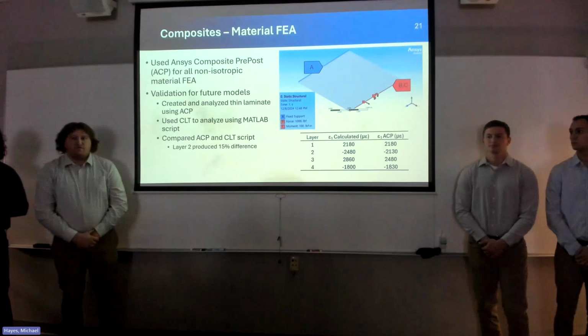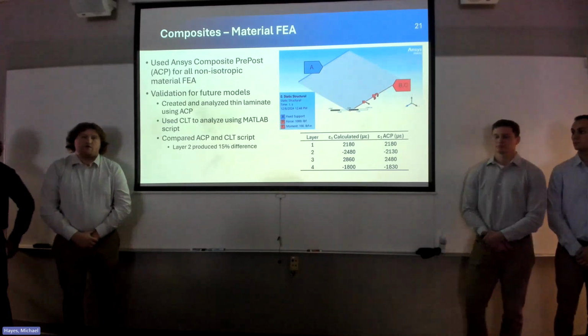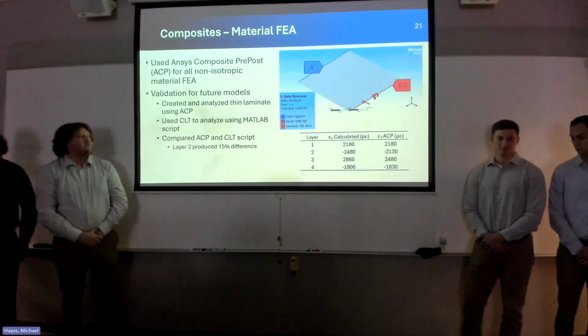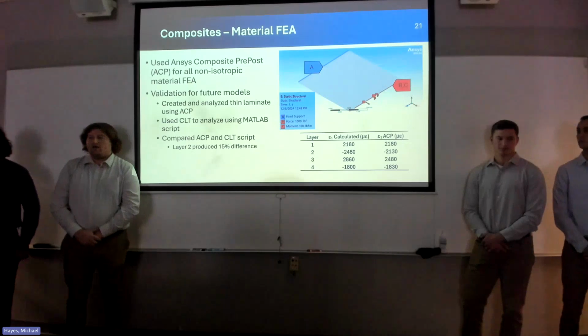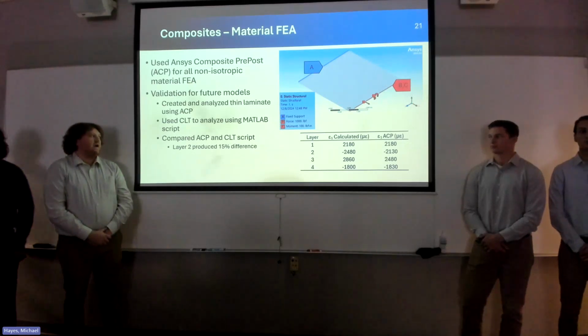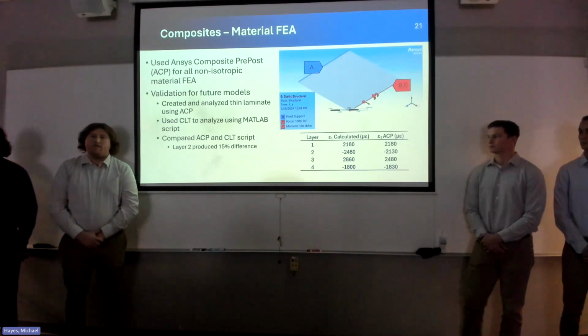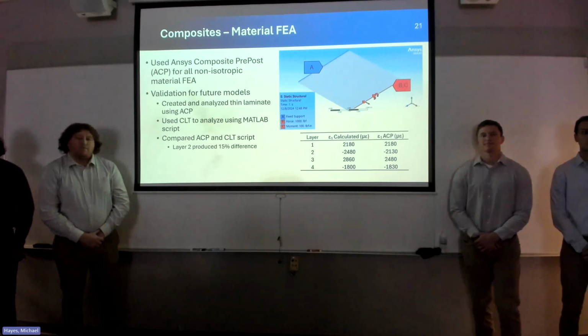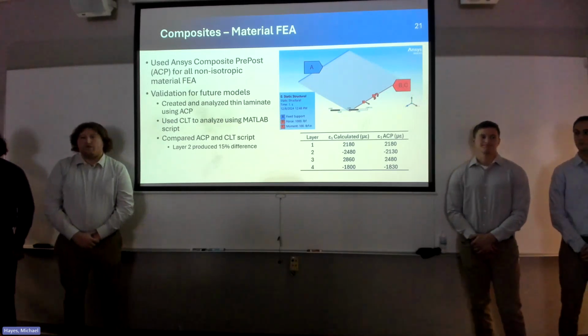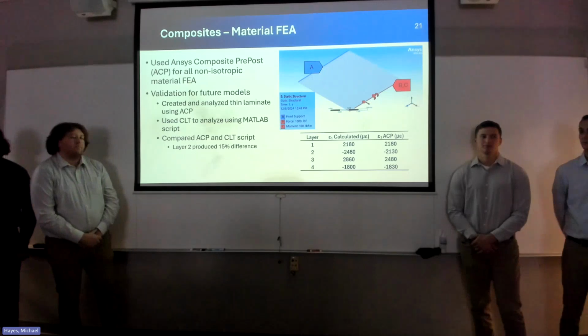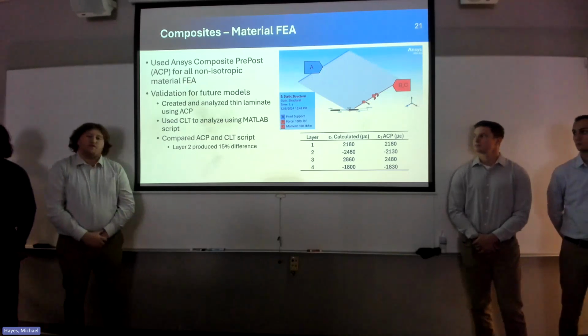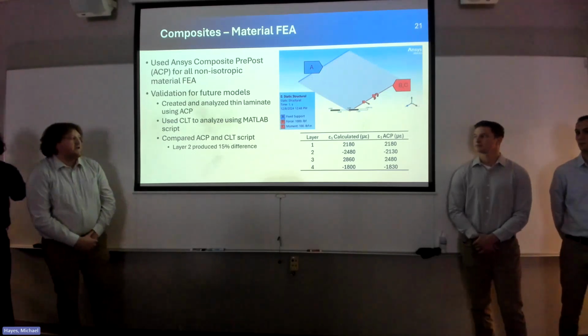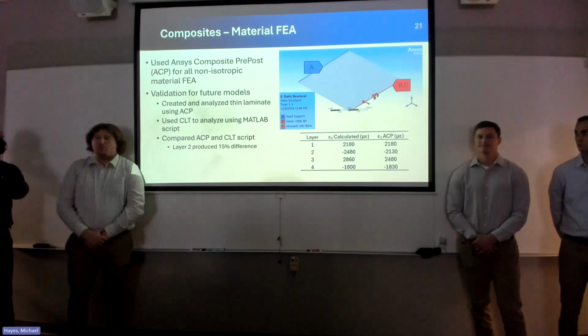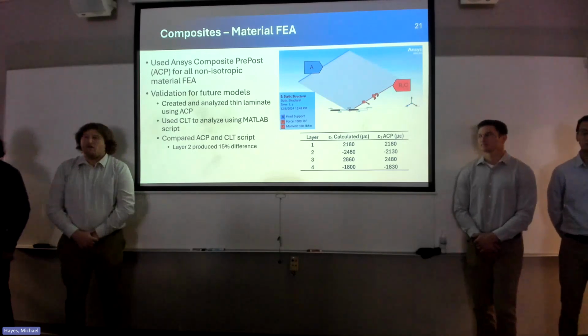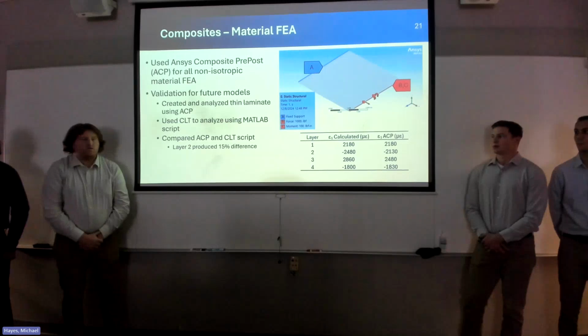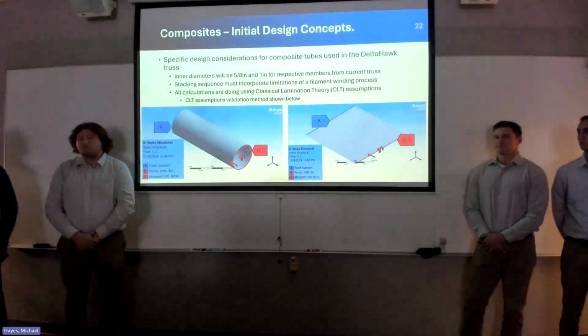I then used ACP's post feature, which lets you analyze the strains in each of the layers and the fiber direction. I compared those strains to what I found using classical lamination theory in a MATLAB script I created. Classical lamination theory assumes that the laminate is a thin plate and makes us take into account primarily just in-plane loads, which simplifies the analysis a little bit. Comparing the ACP and the CLT script, layer 2 produced the highest difference of about 15%. This is not a negligible difference, however, it is not enough to warrant concern.